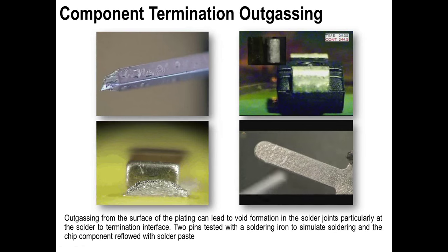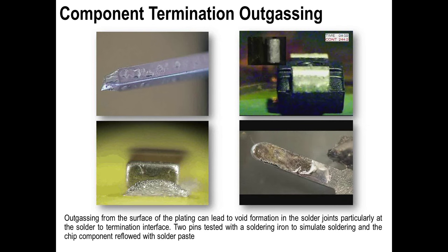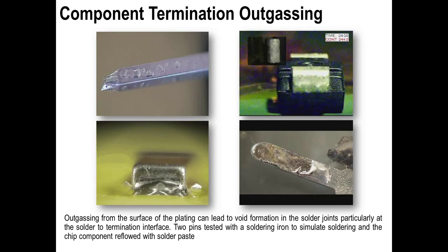If you look at this example, again, bottom right, I'm just showing me tinning a component termination, and look how it de-wets very, very quickly. Now, that action in its own right will cause quite large voids during the soldering process. And quite a lot of you may well have seen this, an old video clip of mine, again showing soldering to a capacitor, where we're successfully soldering and it will be a good join, but you can just make out the bubbling on the surface of the plating. So again, in each of these cases, something on the surface of the plating, probably organics in the plating process, which has contaminated the surface of the terminations, will lead to voids in solder joints. And our first assumption is that it's related to the process or the materials, not necessarily the components. So always look further, look what's actually causing the problem.